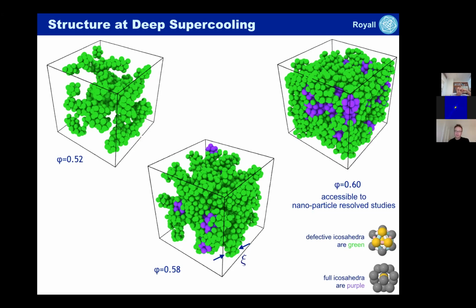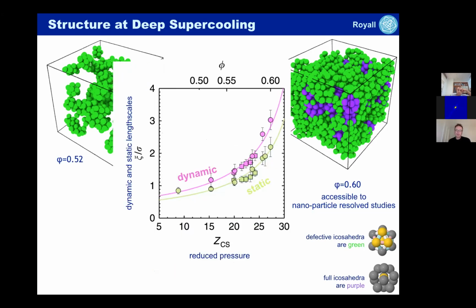So that's fine. We can measure the structural length scale. And what we see now is that the structural length scales are starting to behave more similarly to the dynamic length scales. So there is more hope here that the formation of these defective icosahedra can be some origin of the slow dynamics in this system.